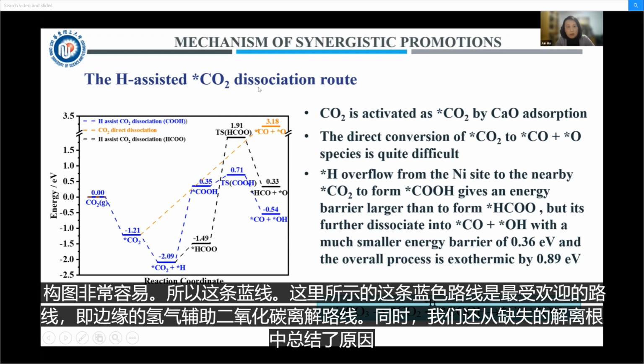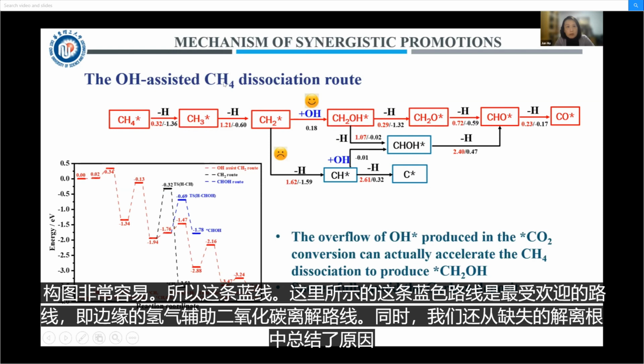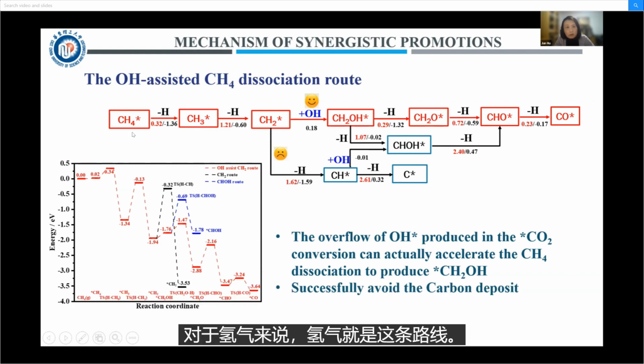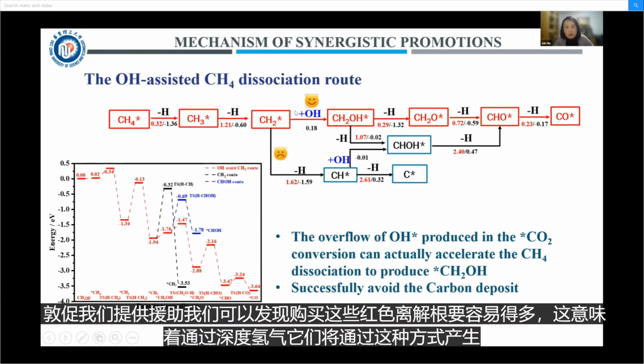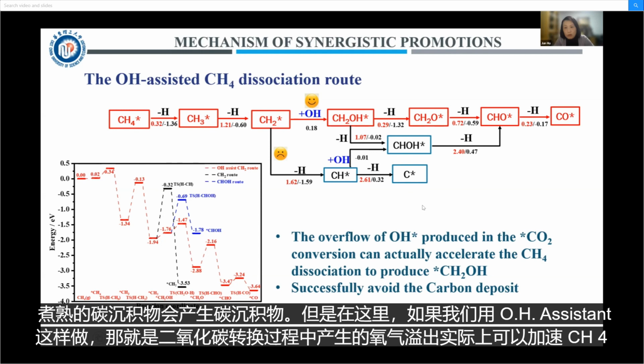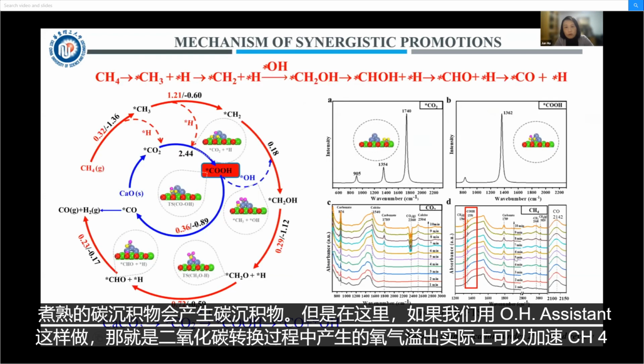Meanwhile, we also found the methane dissociation route, summarized here. The dehydrogenation route is this one. But compared with the OH star assistance, we can find it's much easier by this red dissociation route. That means that by deep dehydrogenation in this way, they will produce coke carbon deposits. But here, if we go this way with the OH assistance, the spillover of OH produced in the CO2 conversion can actually accelerate the CH4 dissociation.